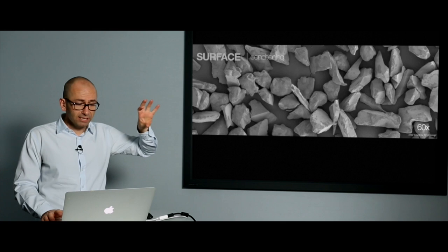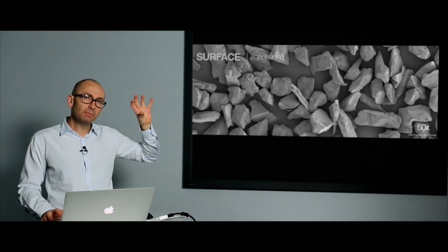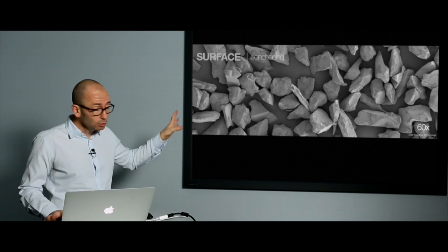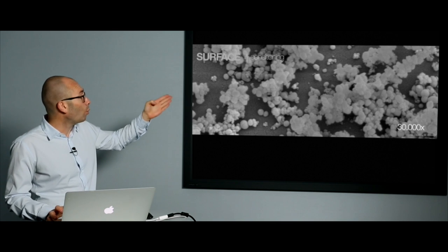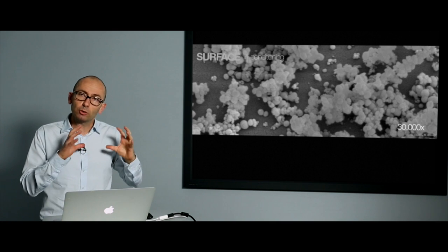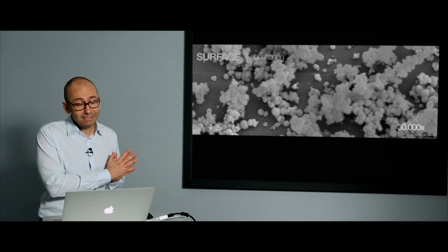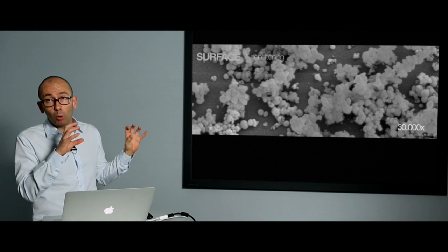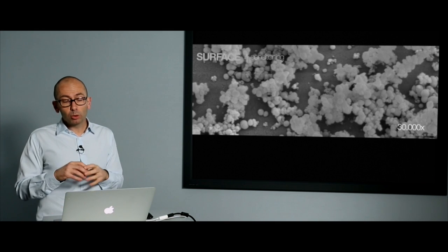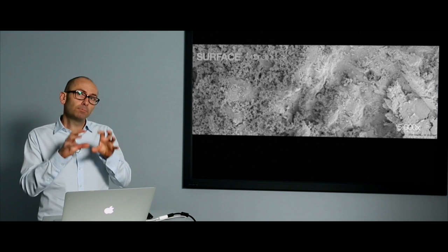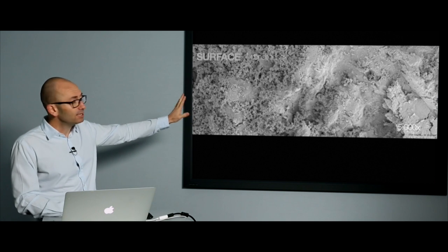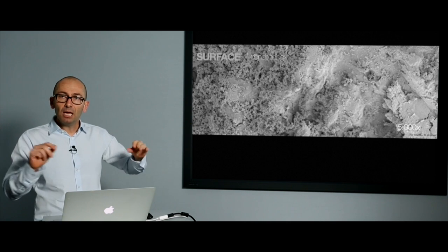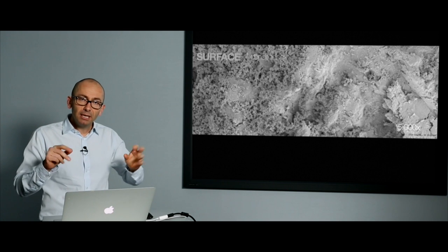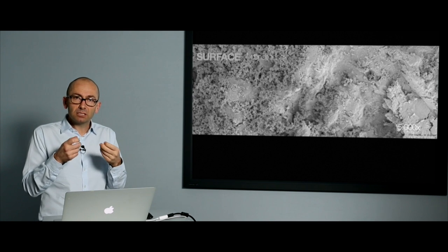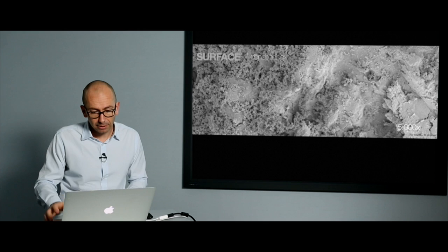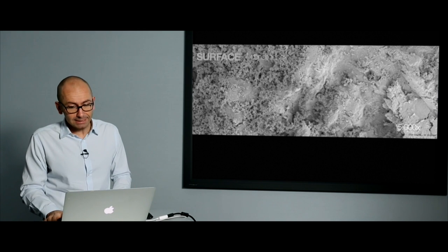Those are more or less about 30 micrometers diameter grains. This is alumina. And if we zoom on one of those grains, this is what you will see. This is silica, the small balls, and the small balls will stay on the composite. This is the composite surface, which is roughened, as you see, with all the balls over it. The surface is just improved to get a better bonding ability.